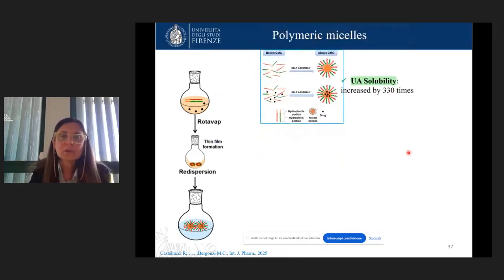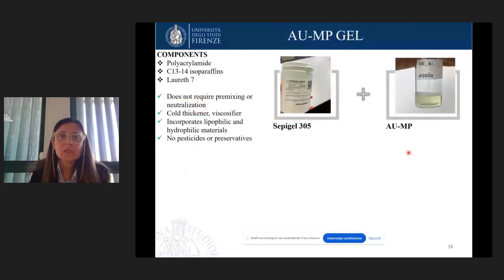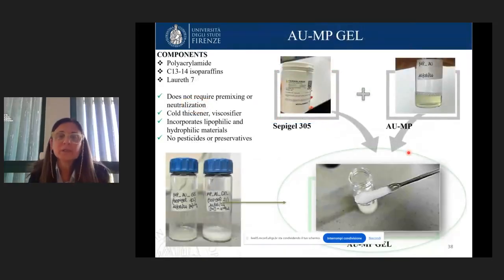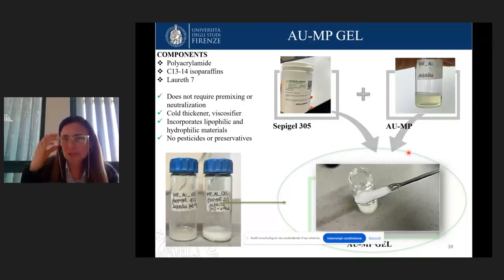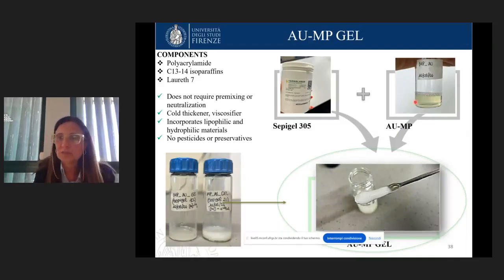And also, we decided to prepare a gel, to prepare topical formulations. First of all, we prepared the colloidal dispersion of micelles that contain usnic acid, and then we gelified this formulation using Sepigel 305 as a gelling agent.